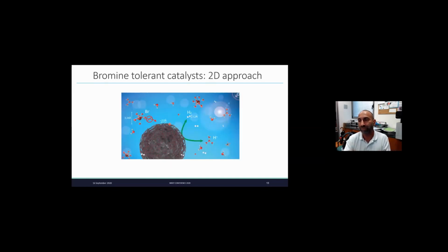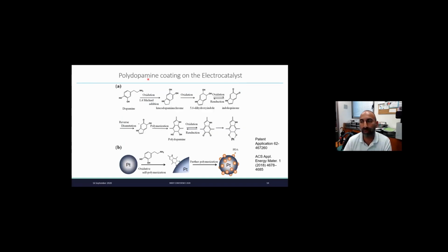So what we did to solve this issue was to design a membrane on top of the catalyst that could filter out the bromine species. So this is a very nice cartoon, and here you have a platinum, and on top of it you have a coating that is only porous to hydrogen and proton, and that is not allowing the diffusion of bromide. So it's done with polydopamine. We like polydopamine. It's a material that is very easy to synthesize. Usually mussels are using that just to stick on the stones in the sea, but you can also use it for other purposes. It was used for lots of application in electrochemistry already.